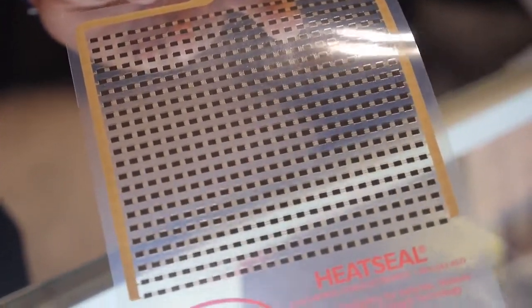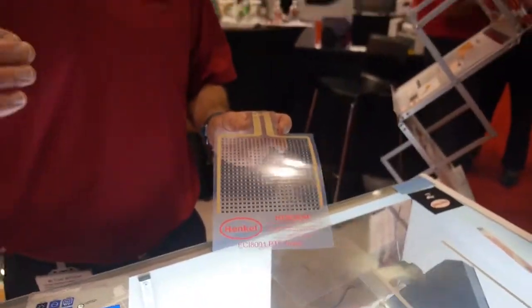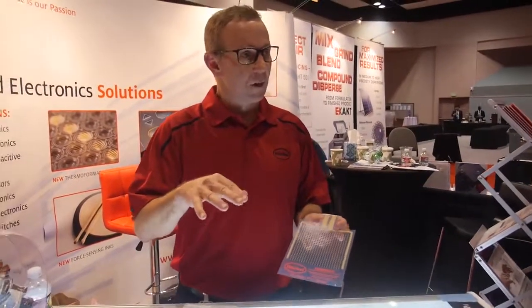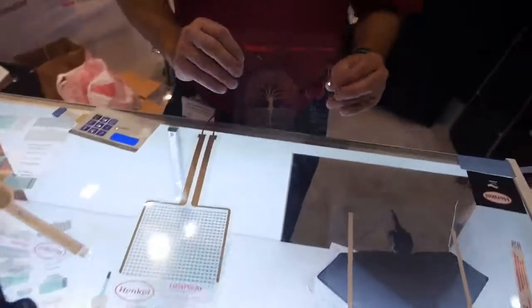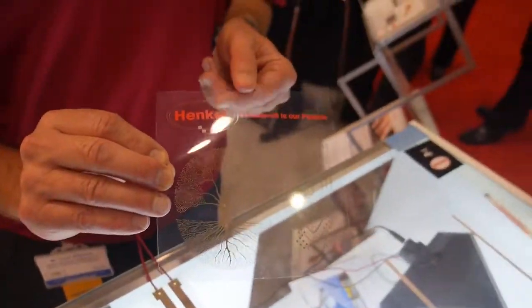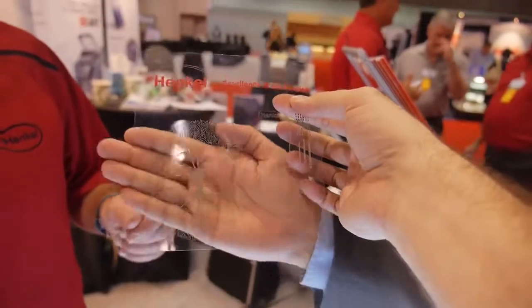You can design the materials between 35 C and 150 C. And the temperature that they're designed at, they'll self-regulate — so if it's 60, it'll be 60 plus or minus about one degree C. The other technology that we have here is a fine line printing technology. You can see this is a typical screen printed circuit, and with that we're able to get down to 60 micron lines and spaces using conventional screen printing.